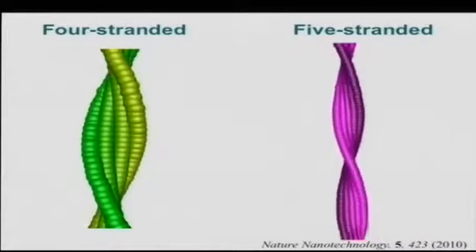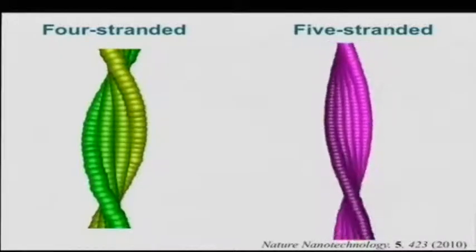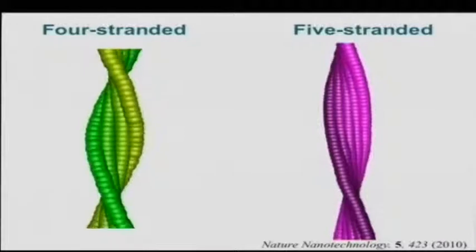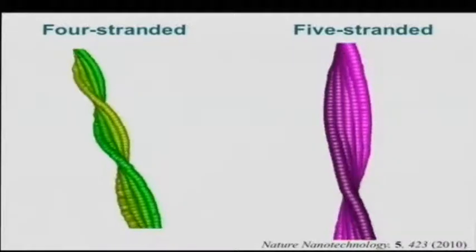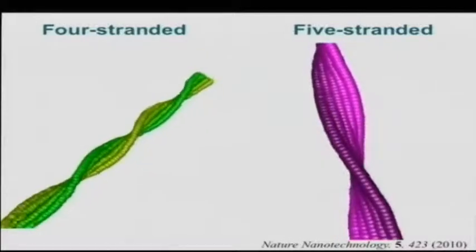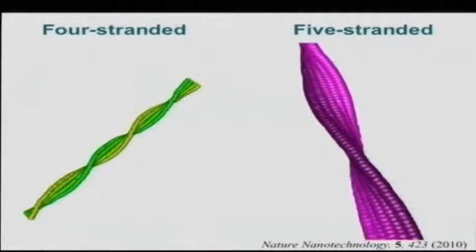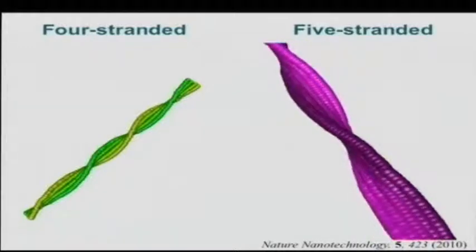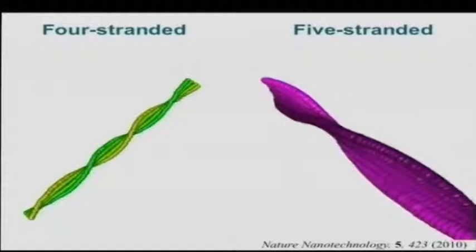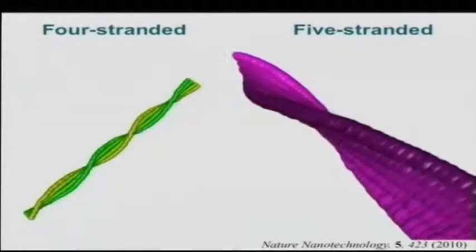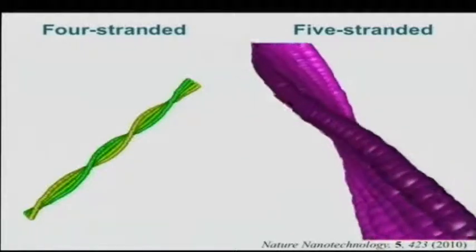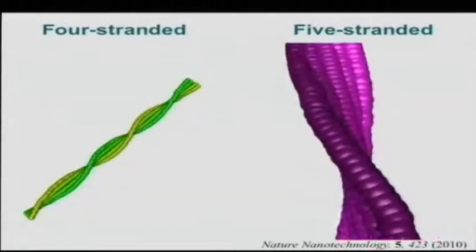What you see here is a coarse-grained molecular dynamics reconstruction of these fibers at the resolution of a single protofilament. This protofilament is about 2 nanometers. And what you see is that the fibers are formed by different protofilaments coming together and twisting, for a number of reasons which depend on the electrostatic repulsion, elastic energy along the fibers, and chirality, because all these fibers are left-handed.